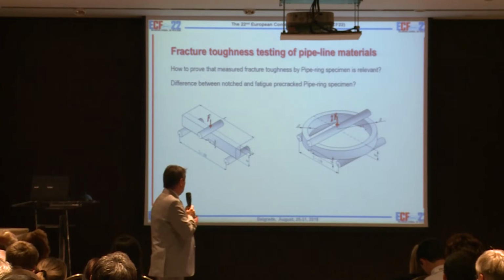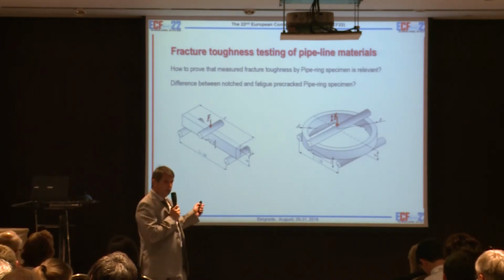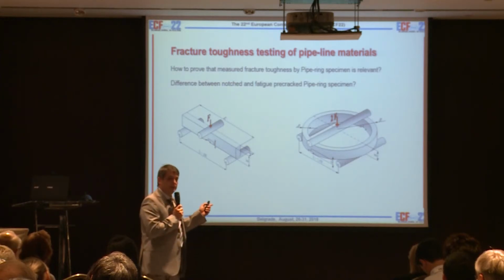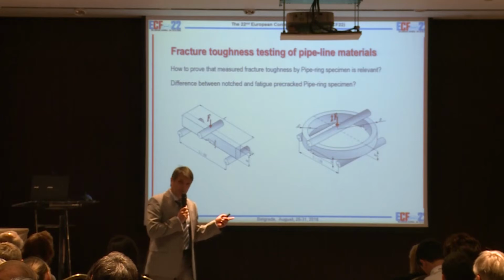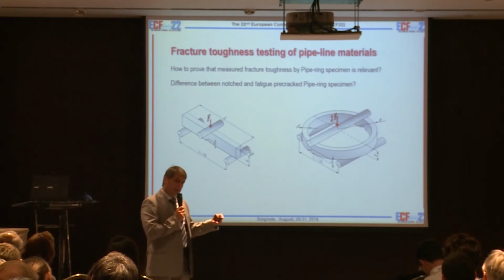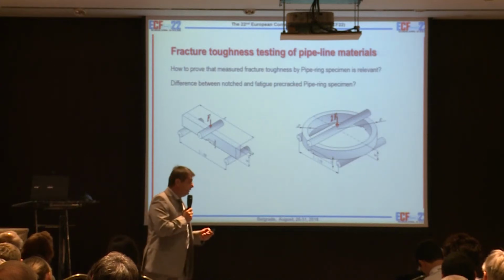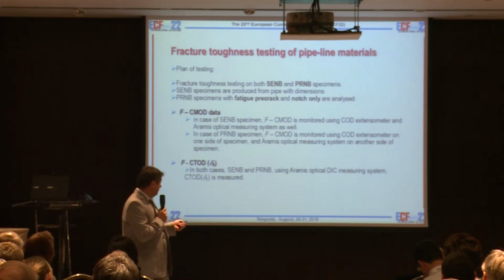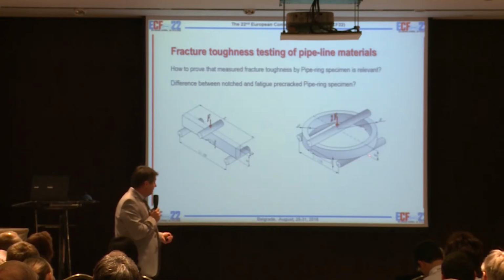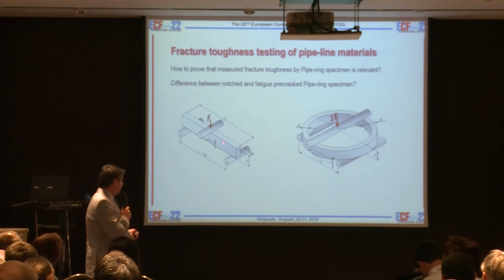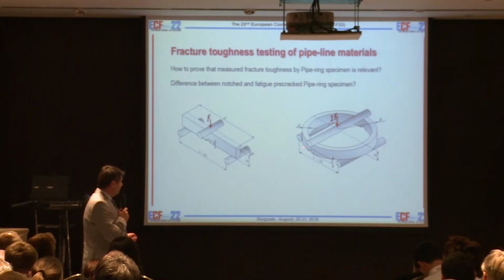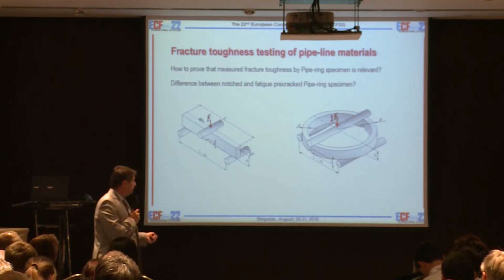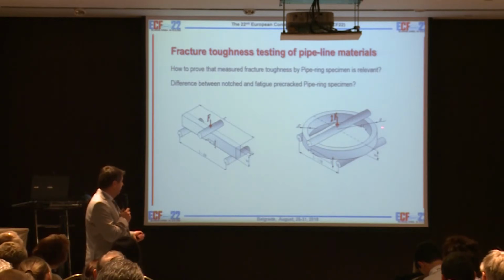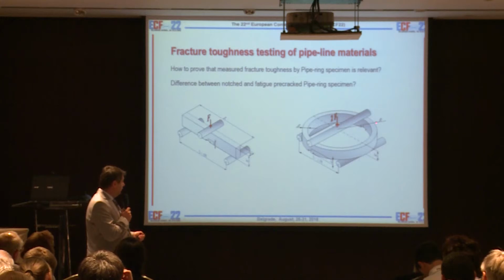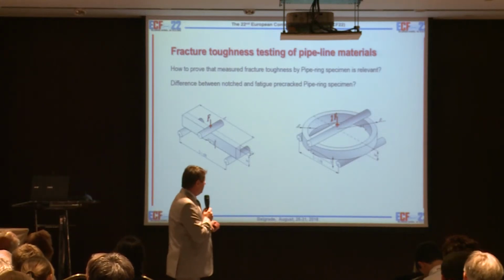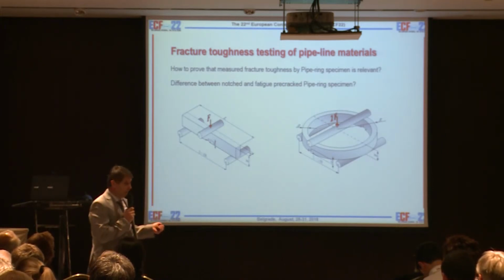So first is how to prove that the toughness which we measured on the 3-point bend specimen is the same or similar to that of the pipe ring specimen. In this way we use the same material. First we cut it by spark eroding from the plate, because we want to avoid residual stresses, and then we made this geometry here, and we keep the width at 2 times the thickness, similar to the standard 3-point bend specimen. We also use a distance between pins of 0.9 diameter, and we have different thickness over radius ratios. Of course the force which we applied is double, because it is like two 3-point bend specimens.